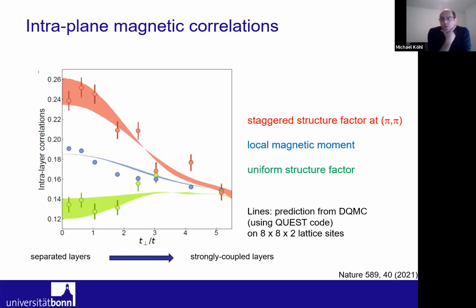And we have basically two ways that we can compare with. One is the uniform structure factor. So that is basically measuring without the spin rotation the same thing. And this gives us the baseline. That is, these are the green data points down here. And the other thing is the local magnetic moment. So that is just the distribution of the on-site spins without taking into account nearest neighbor correlations. And these are the blue data points.